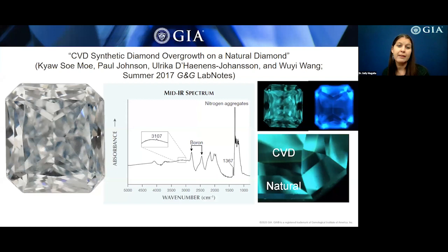So in the summer of 2017, GIA saw its first example of a client-submitted CVD overgrowth on natural diamond. Now, GIA had researched this eventuality for years, and we knew what to look for and what to expect. Only a very thin layer is necessary to have a dramatic effect on the stone's color. So this 0.33 carat fancy blue diamond was confirmed to be a composite of CVD laboratory grown type 2B diamond overgrowth on a natural type 1A substrate.